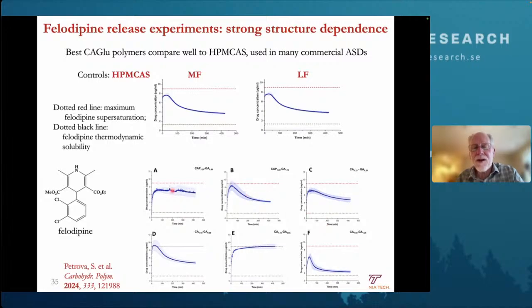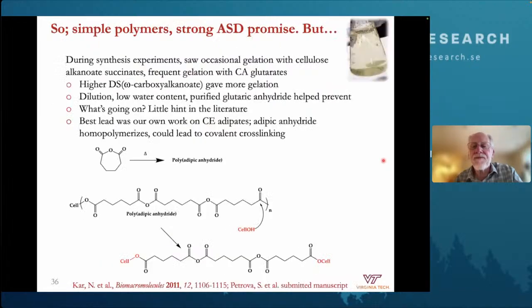And what you see is all of them help. All of them give concentrations of felodipine above the thermodynamic solubility. But look at polymer E, the cellulose acetate glutarate. The concentration rapidly gets up to the maximum possible supersaturation and it stays there, for the entire time this dosage form would be in the absorptive portion of the GI tract. In other words, the performance is as good as it possibly could be. And it's a simple cellulose acetate glutarate.